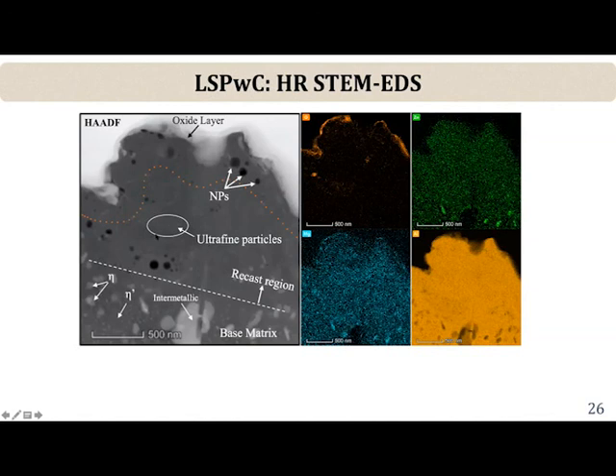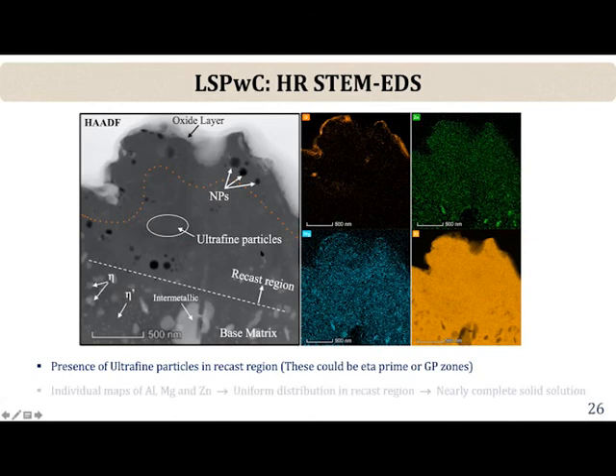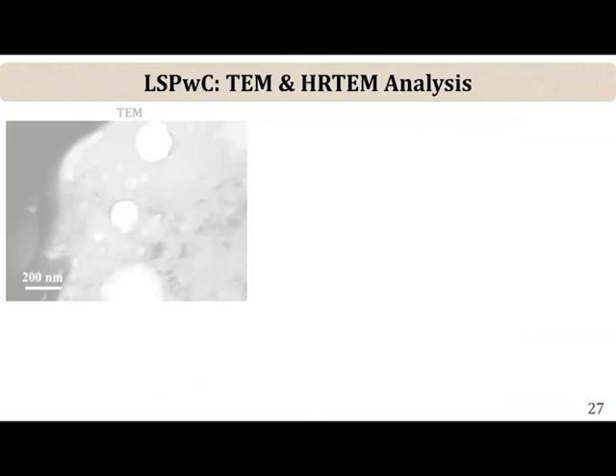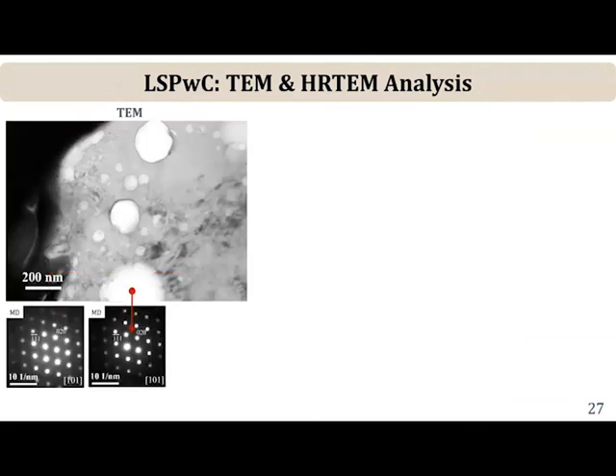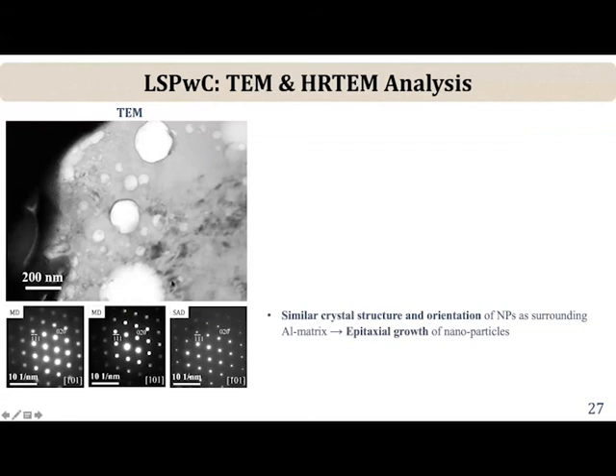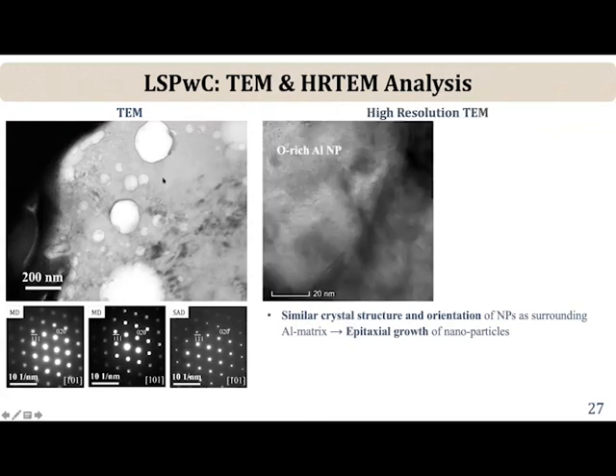You have some very ultra fine precipitates and you have these nanoparticles on the surface. These could be eta prime or they could be GP zones, which are known to form even at room temperature. You can have an aluminum 7075 alloy sitting at room temperature and you can get precipitation at room temperature. So some of these fine particles could have been produced that way. But the important point here is that the diffraction evidence, these are micro diffraction patterns taken from individual particles, shows that these are aluminum enriched in oxygen.